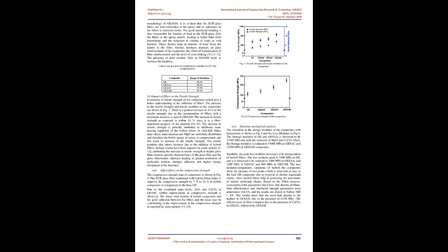G. Effect of fillers on volume and surface resistivity. The results of volume resistivity of the composites in the as-received condition and after 500 h immersion in water are shown in Table 9 and Table X respectively. The composites with hybrid fillers incorporated show better volume and surface resistivity as compared to the base composite. Further, the reduction in volume resistivity or surface resistivity after immersion in water is relatively lower as compared to the base composites, mainly due to the presence of fillers.